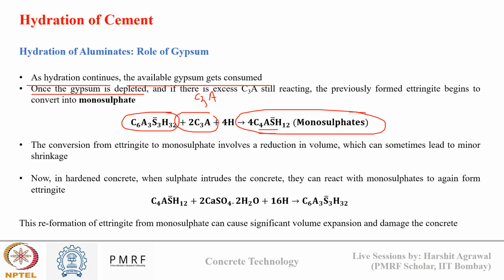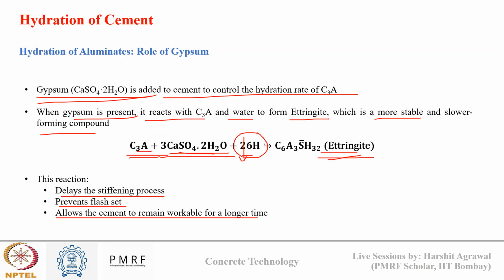This conversion of ettringite to monosulfate involves a reduction in volume. Suppose its volume was 1 meter cube, the volume of monosulfate will be around 0.8 meter cube. So there is a reduction in volume due to this reaction, which can lead to some shrinkage problem. But the important thing is that the reaction which was causing flash setting in cement is now delayed due to the presence of gypsum.